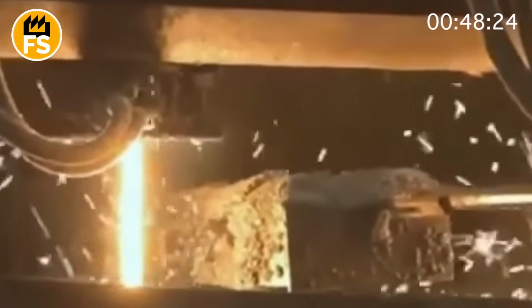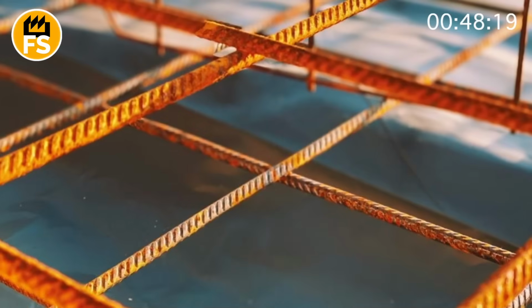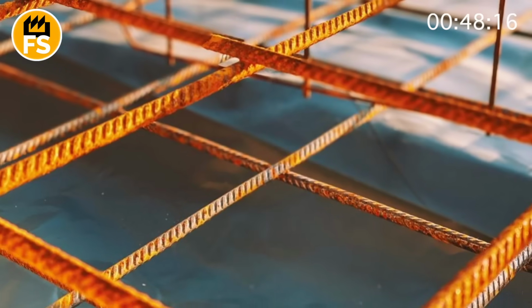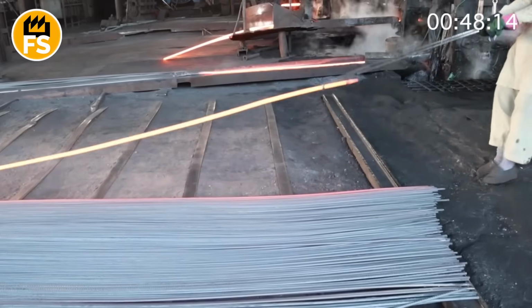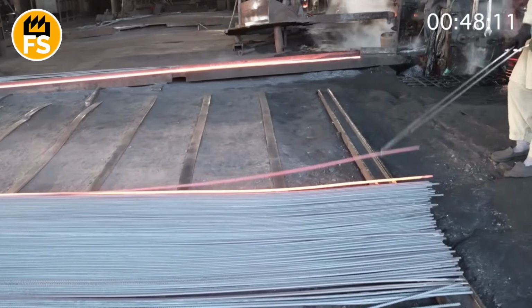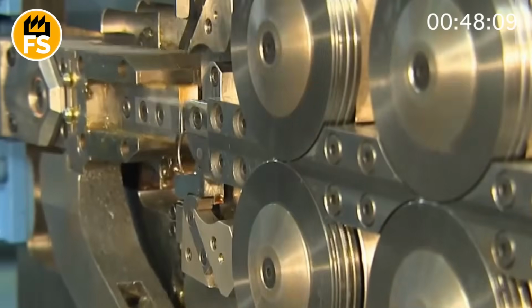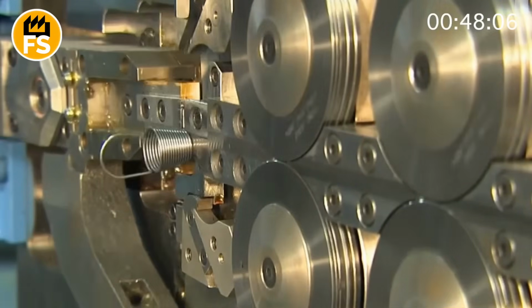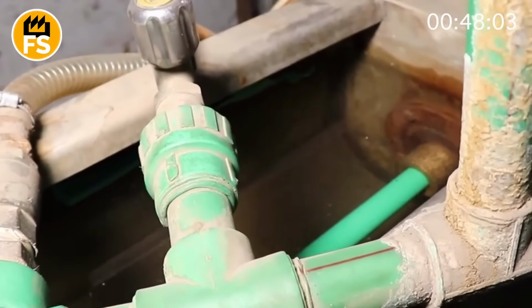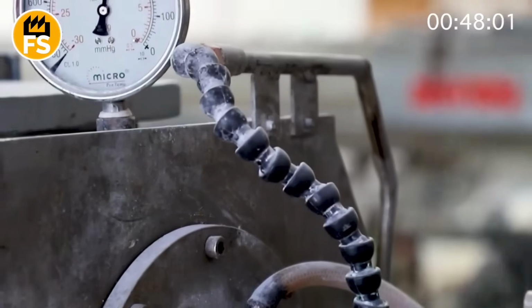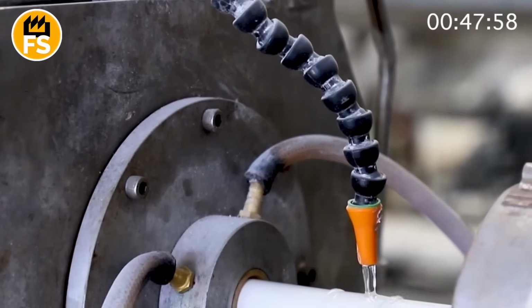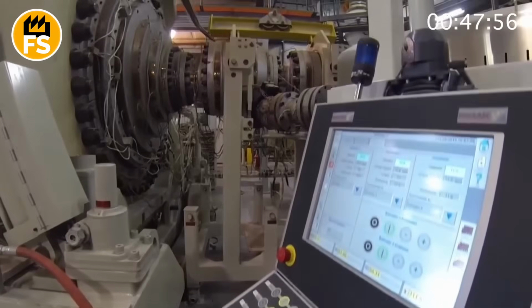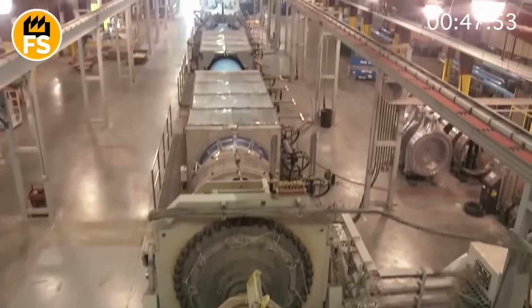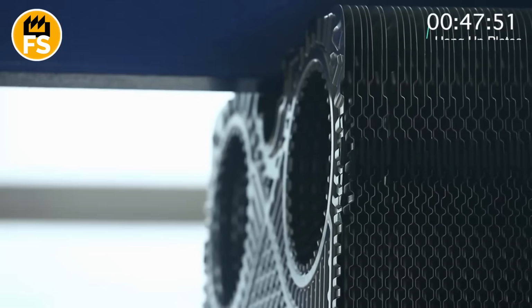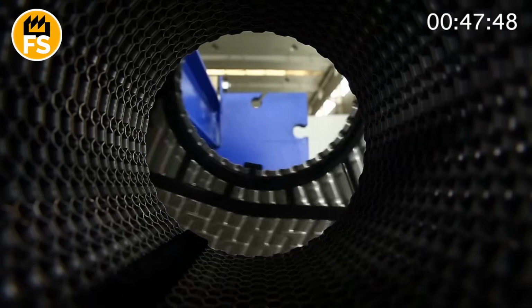To fix all the parts, bolts up to 1.5 inches in diameter are used, tightened with special hydraulic torque wrenches. One such bolt can withstand a load of tens of thousands of pounds. The finished spool is installed on a temporary axle and rotated. Engineers check the balance using a laser level, ensuring that during rotation, no part shifts even 1/4 inch. If the structure wobbles, it's ground, adjusted, and sometimes parts of the elements are reassembled. And only after this is the spool considered ready for the final stage: anti-corrosion treatment, painting, and testing.